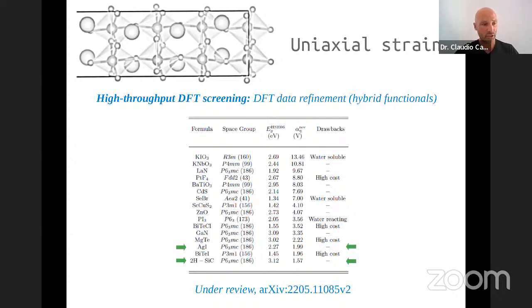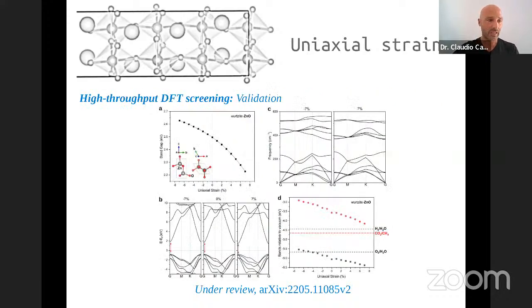So in the final positions, we have silver iodide and silicon carbide, which are very well-known materials and which have quite optimal properties. Also, they are very cheap. So these two are probably pretty good candidates for scalability purposes. Okay, so that was the result of our high throughput screen just based on the value of this alpha descriptor.